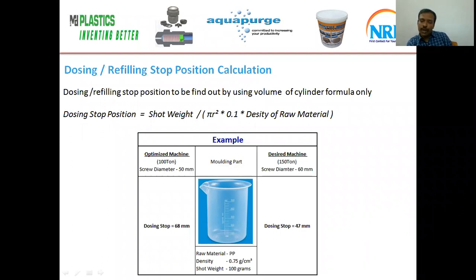I have already run that bigger part in a 100 ton machine. The 100 ton machine has a screw diameter of 50 mm, so the dosing stop is 68 mm. Now I am planning to run this part in the 150 ton machine, which has a screw diameter of 60 mm. By using this calculation, the dosing stop comes to 47 mm. So when screw diameter increases, the screw stroke reduces.